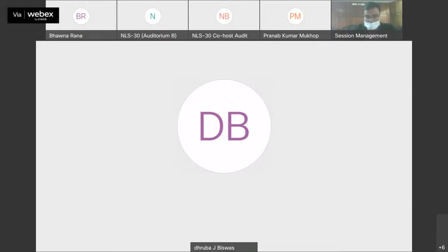Okay. Did you compare your results with and without Axicon? Yes, sir. We have compared the results with Gaussian beam also, that means with some other lens, and with Axicon we have compared. These results are at least like 3 orders better in terms of surface enhanced Raman scattering enhancement. That means in terms of the plasmonic response which is coming out of the finger-like nanostructures,